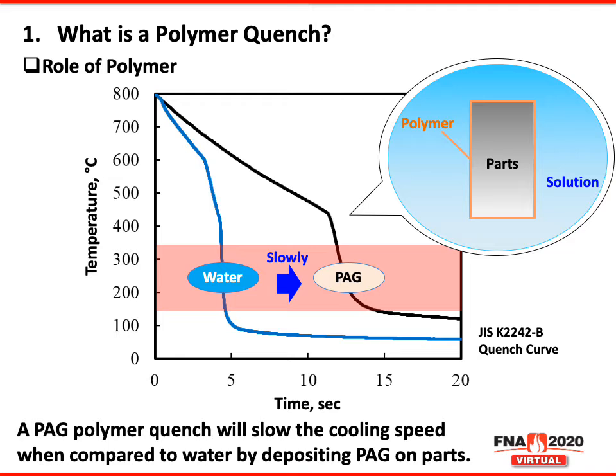So what that means is the polymer, when it comes out of solution, you can see here, it coats the part and controls the cooling. It creates a long vapor phase, and then into your boiling phase, and then into the convection phase. Where if it were just water, it would have a short vapor phase. And you notice that this portion here of the boiling phase, the slope of that line is very steep and it's very rapid. And then the PAG, the polyethylene glycol, lessens that slope and it controls the cooling better.